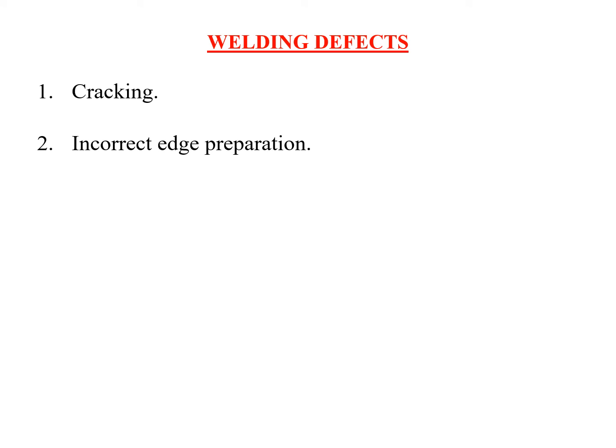The next defect is incorrect edge preparation. In edge preparation we chamfer or apply a fillet at a certain angle with a set distance between the two components to be welded. If the angle is too narrow, it results in poor fusion, slag inclusions, and a weaker weld. If the angle is too wide, it results in heavy welding, overheating, and locked-up thermal stresses induced inside the component.